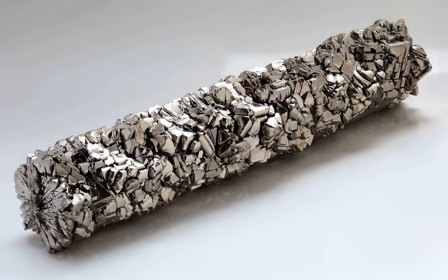All welding of titanium must be done in an inert atmosphere of argon or helium to shield it from contamination with atmospheric gases: oxygen, nitrogen, and hydrogen. Contamination causes a variety of conditions, such as embrittlement, which reduce the integrity of the assembly welds and lead to joint failure.